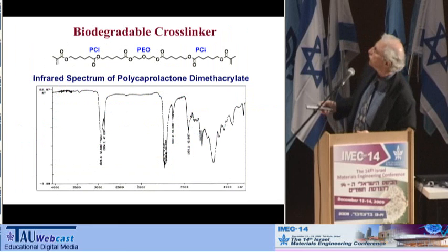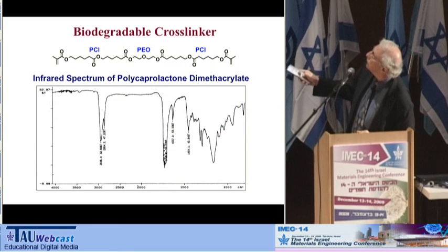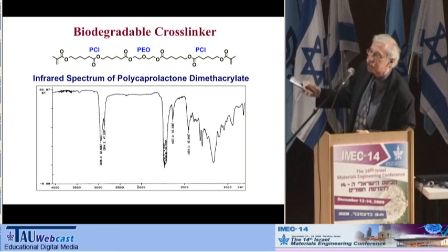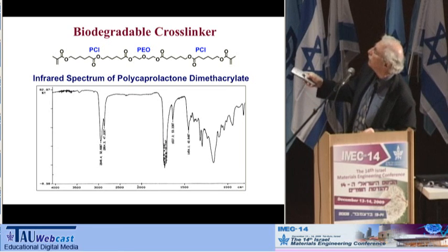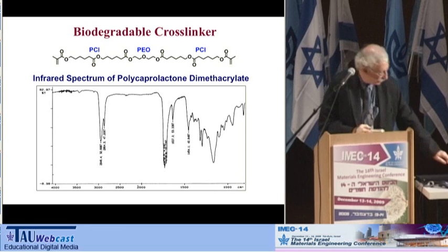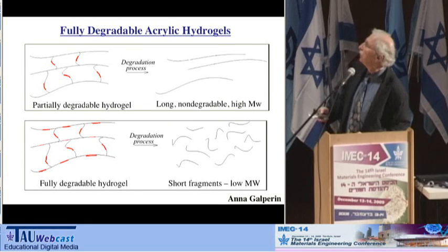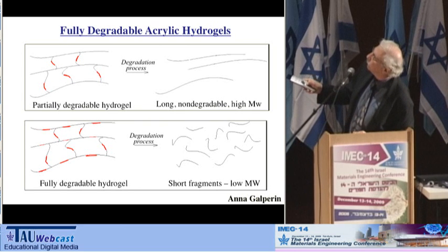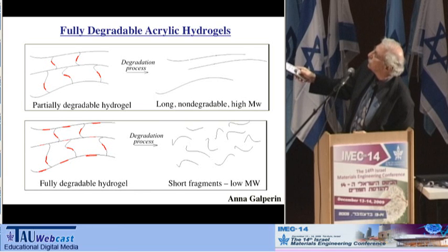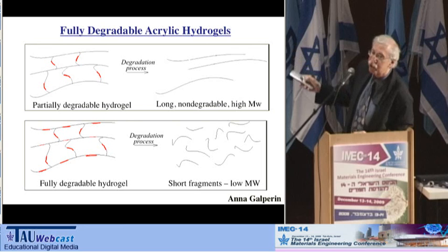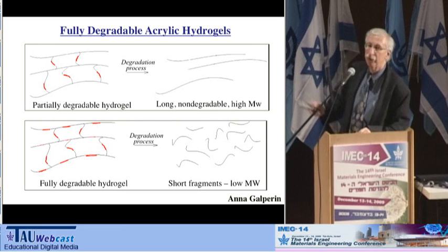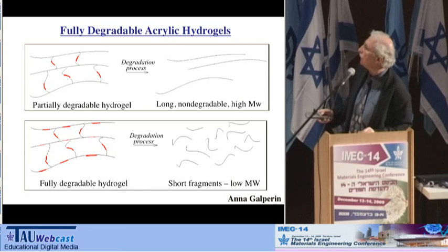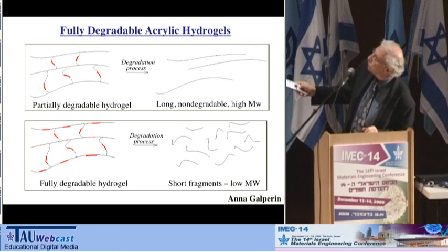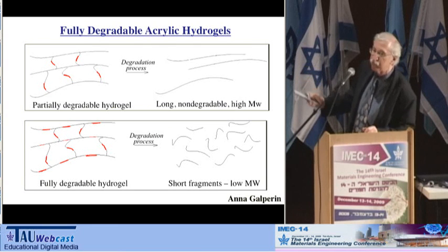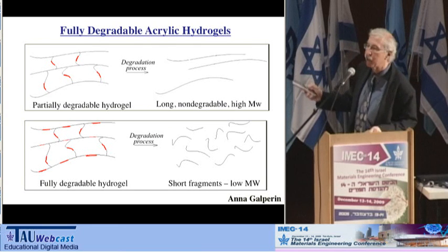We developed a crosslinker that has polyester units, polycaprolactone units, which breaks down into caproic acid, part of normal metabolism. This just talks about some of the organic chemistry that went into that. But the general idea is, if we just took the HEMA chains and cross-linked them, with the red being the degradable crosslinker units, and they degrade, we'll still have these long, non-degradable, non-water-soluble, high molecular weight HEMA chains that the body really can't clear or degrade. So the idea is to put backbone linkages in too, and then when the whole thing breaks down, it's in little fragments. The short fragments can be soluble and can be cleared through the kidney.